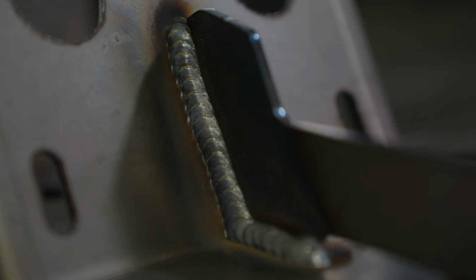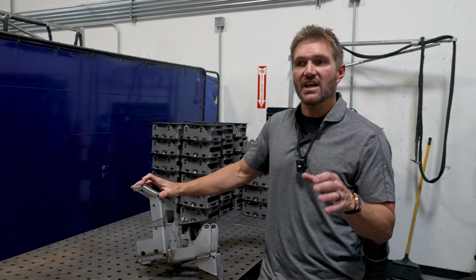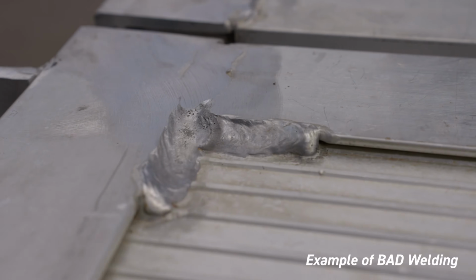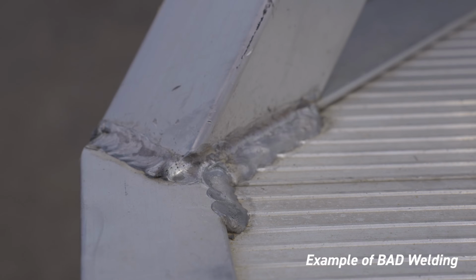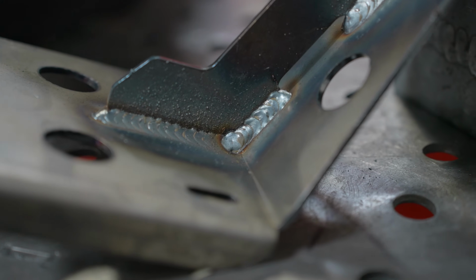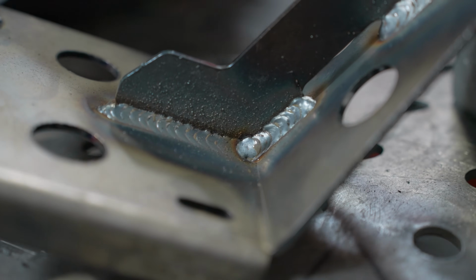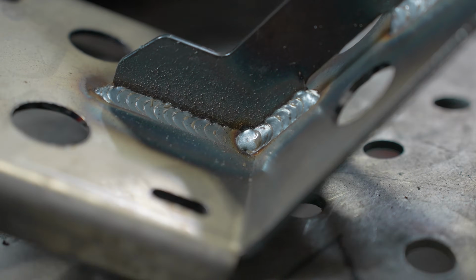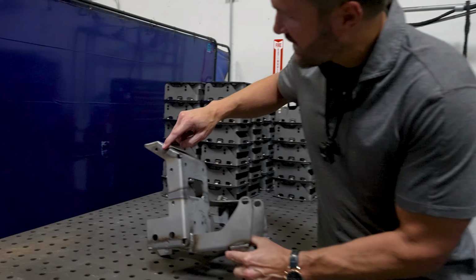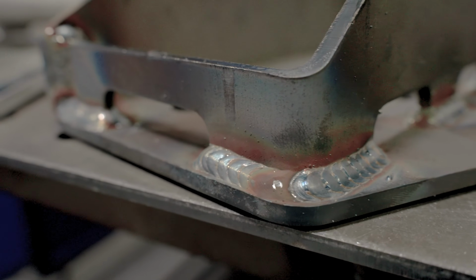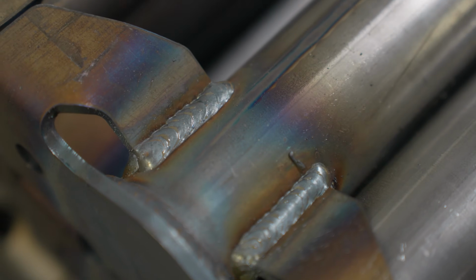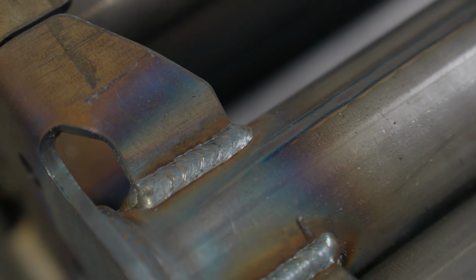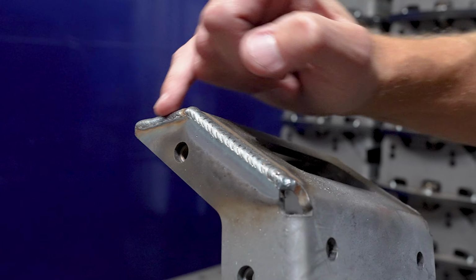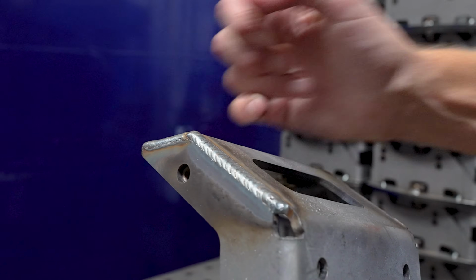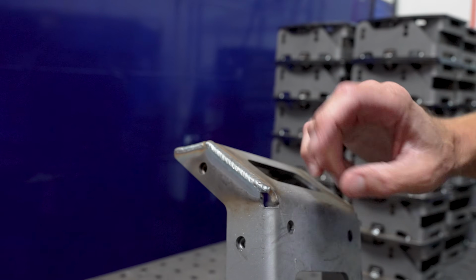And I encourage you to start looking at places like amusement parks, ski lifts. Look at the welds on those items. What you want to see in a good weld, and I can show you on this one down here, is that it lays down real flat. You see how this one sits on the corner? You have what's called stacking dimes, so you see basically the contours of each part of the weld as it goes. There's no starts and stops, but you see how this part's raised?